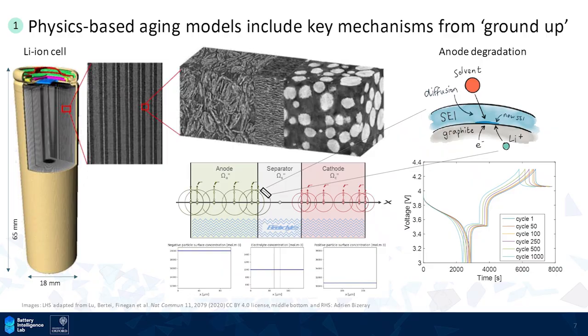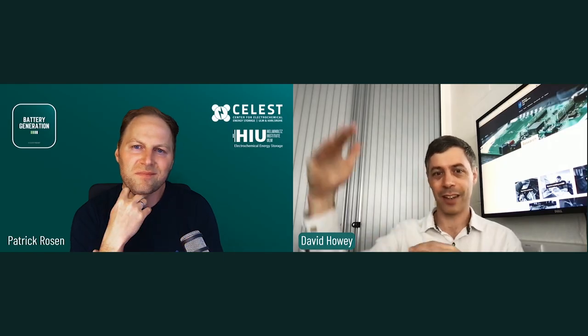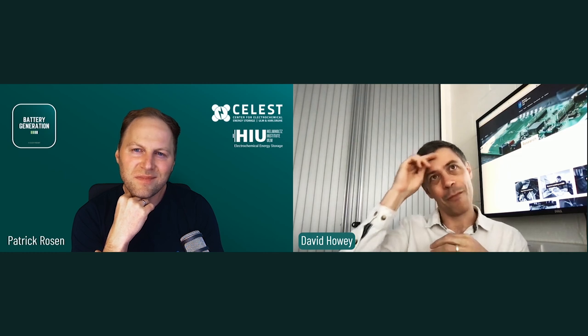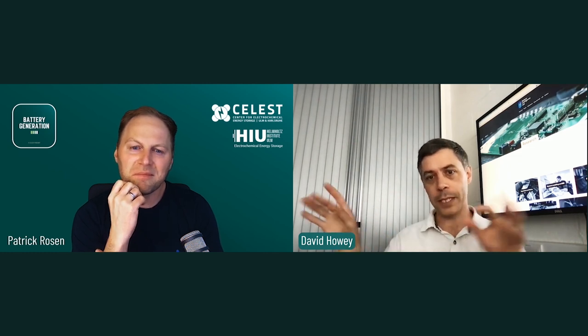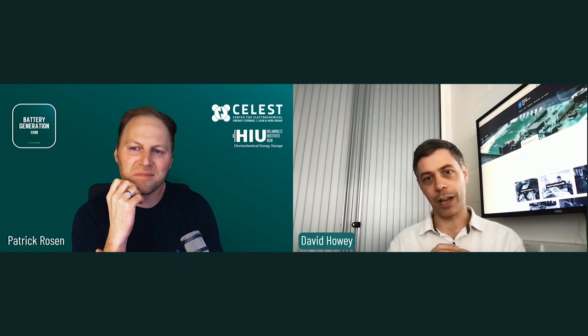But yeah, that's what can happen when you deep discharge or leave the battery at very low voltage, and the voltage starts to go below the voltage where we essentially start to dissolve the current collectors. So we have aluminium and copper in there. And if I remember correctly, I think it's the copper that dissolves at a lower voltage. And so that starts to cause bits of copper to float around in the electrolyte, and then it can start to cause degradation of the electrolyte, and we can have what you saw here.